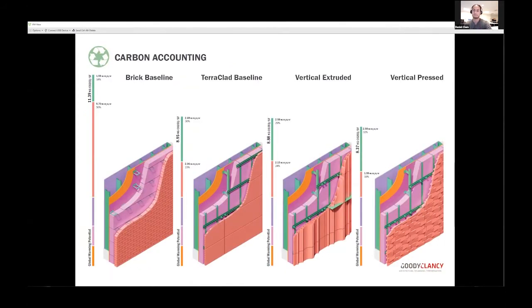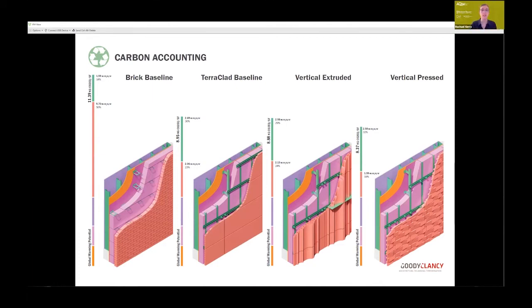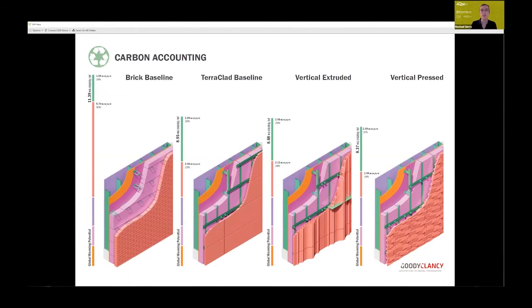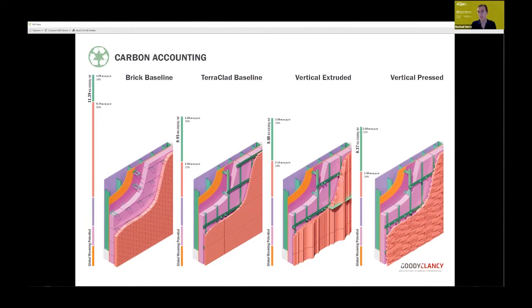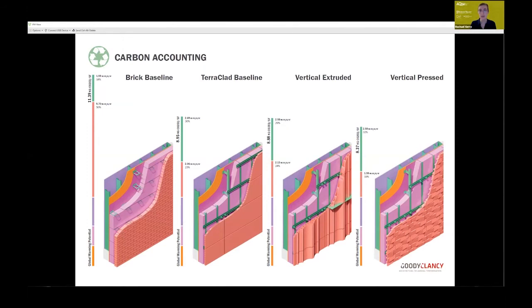Similar to daylighting, we looked at carbon footprint throughout the design process to compare different schemes. We learned early on that the two biggest factors we can manipulate to decrease overall carbon footprint are the volume of clay in the system and the amount of metal backup structure required to hold it up. We discovered ram press modules had the least clay volume per square foot because you could hollow out the entire back, versus an extruded scheme hollowed only at the core.